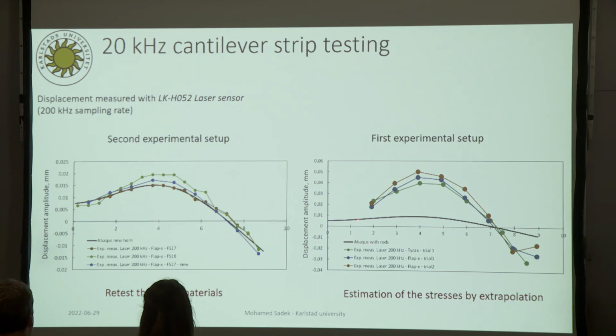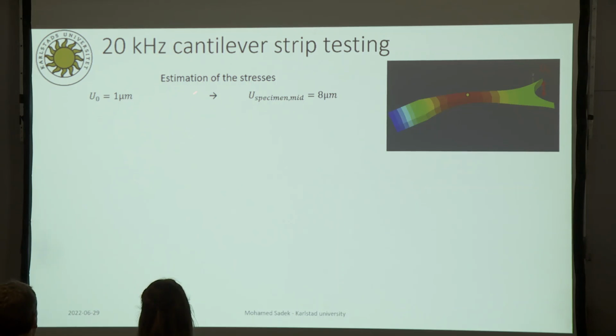From the laser measurement, we could see that the relationship between U0, which is the displacement at the horn, and the displacement in the middle of the specimen is approximately 1 to 8. For every 1 micrometer at the beginning, we will get approximately 8 micrometer displacement in the middle of the specimen. So that is the first rule that we will use for the estimation. 1 micrometer in U0 will correspond to 8 micrometer displacement in the middle.